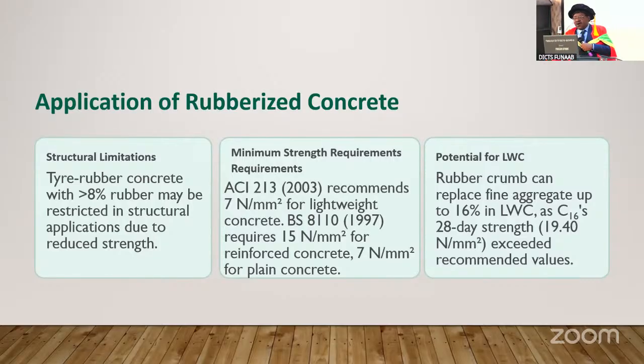From our result, the rubber crumb can replace fine aggregate up to 16% in lightweight concrete, because our C16, which is the least, has 19.40, which exceeded the recommended value. That is the catch, because it's greater than the value the standard said we should use.